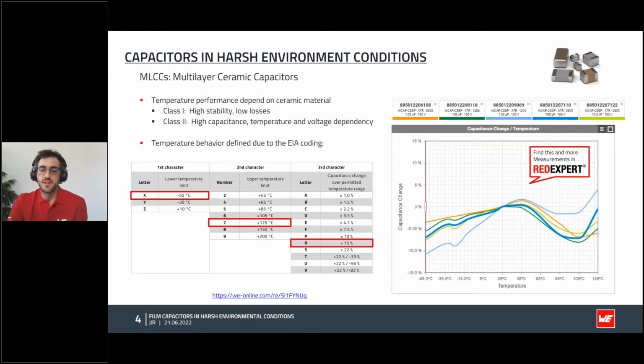Class 2 materials are actually classified by the thermal performance of the component. As specified by the EIA coding that you can see in the slide, there is the very common specification X7R, which means a temperature range of -55 degrees to 125 degrees maximum, as well as a permitted capacitance deviation of plus minus 15% in that range. On the right, you can see the capacitance deviation of several X7R capacitors of 100 volt voltage rating.